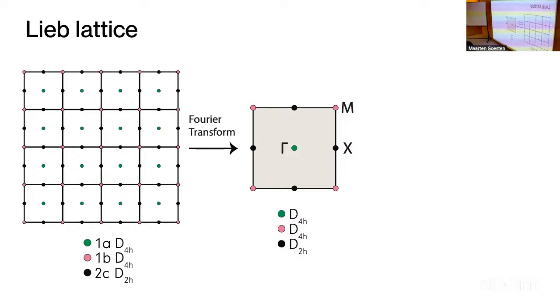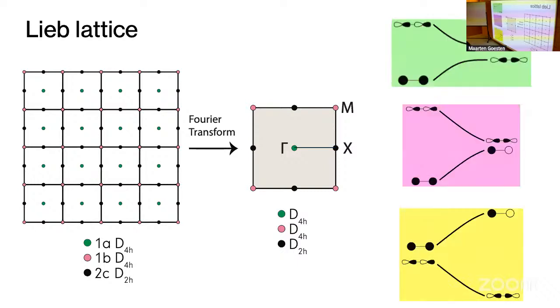When you Fourier transform that, and that's why I said the Fourier transform generally looks like the original object to some degree, your Wyckoff positions become high symmetry points. And then it's the group of the wave vector which determines the symmetry and the point group of the wave function. It determines all the operations that map the wave function onto itself. And that's what you get here. You get in that case gamma, which is always the full point group of the lattice. But we have, for instance, another point M, where the wave function will also have to be fixed by all the operations of the D4h point group. So what you want with topological quantum chemistry is to have control over the orbitals at different Wyckoff positions. This is how you design a topological material.